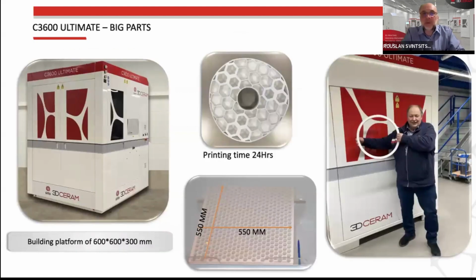And finally, when we speak of the big machine, it can be used for even bigger output, but particularly for the printing of big parts, because in space we also need some big parts, typically the supports of different astronavigation systems, astronavigation tools. Here you see an example of a circular part with specific cavities, which cannot be done by injection molding. So those were printed, and the diameter of this part is 450 millimeters. Just under, you can see another demo structure, a kind of honeycomb structure, 550 by 550 millimeters.